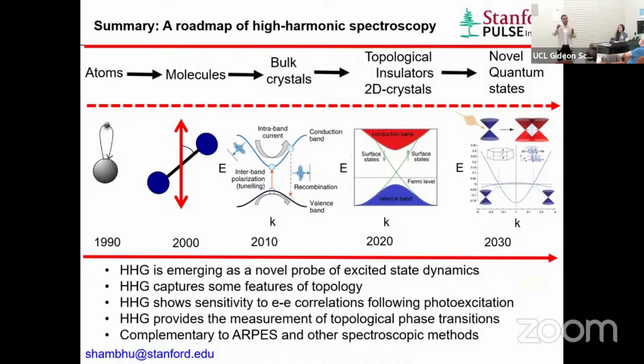Perhaps not as efficiently as if you are rescattering from the same site, but the circular polarization, even in systems like magnesium oxide that don't need to be topologically non-trivial, is one of the remarkable differences. Yes, unfortunately polarization gating would not work, but I'm pretty happy with the circular field being a way to probe the topological surface states, because this is more efficient for the circular field.